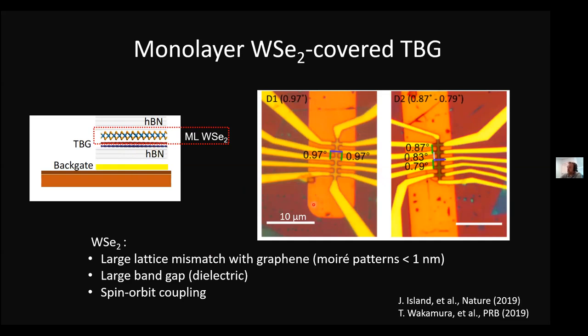And this is just the optical image of the two devices that I will talk about. Both of them are smaller than the magic angle. The first one is 0.97 degrees, and the second device has a range of contacts ranging from 0.87 to 0.79.